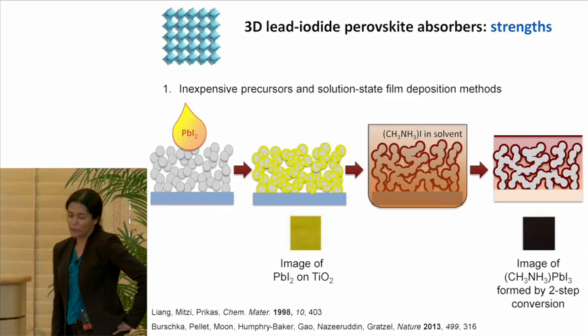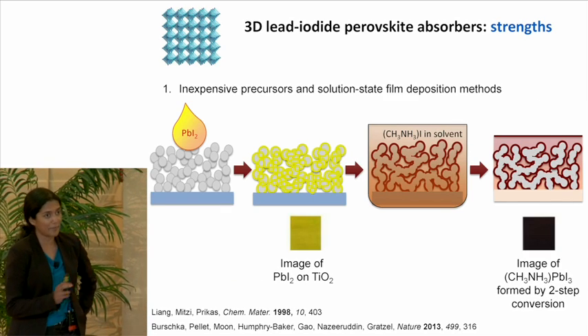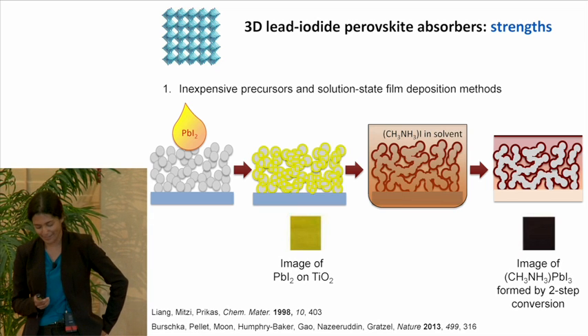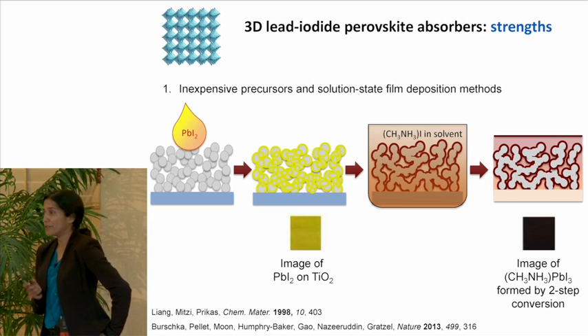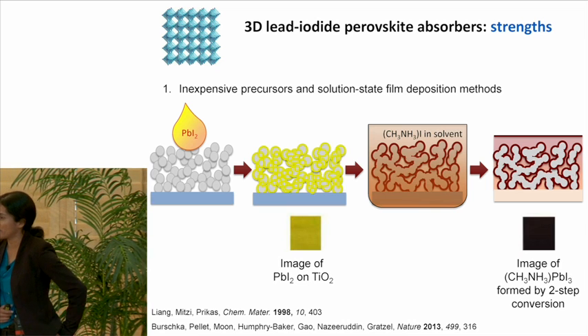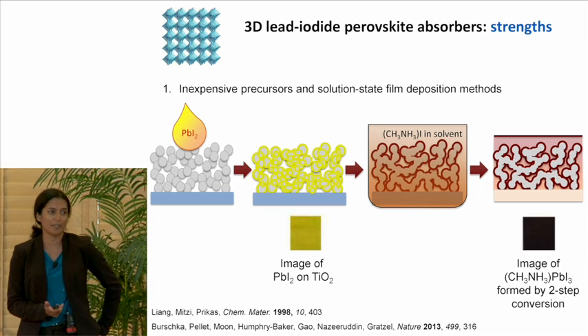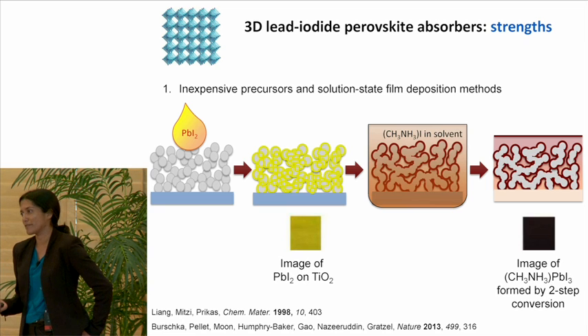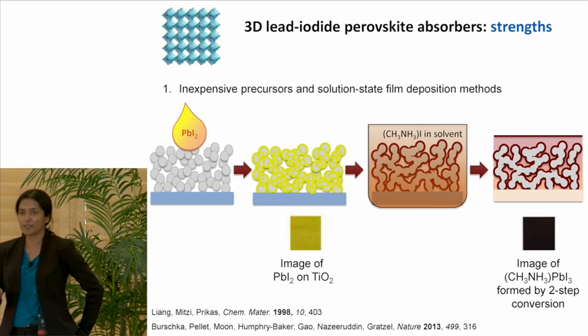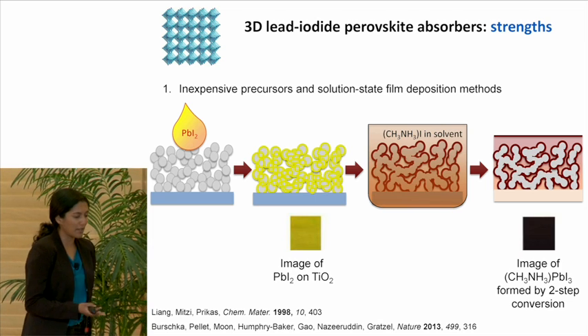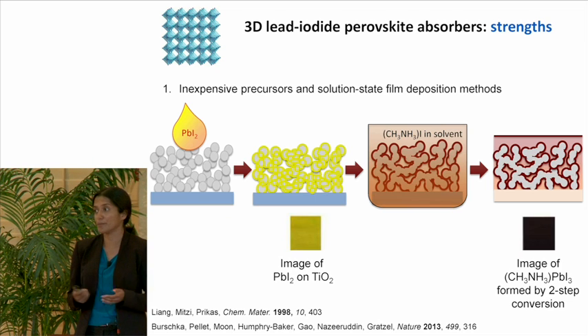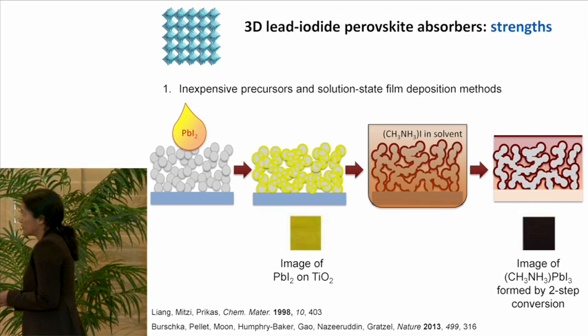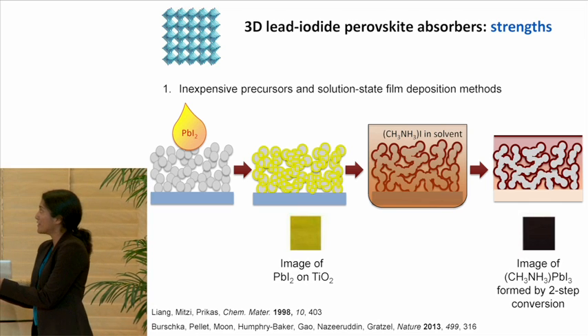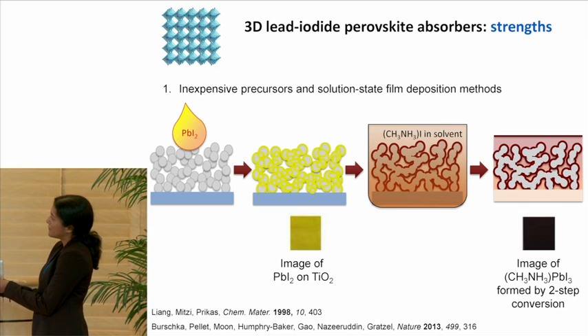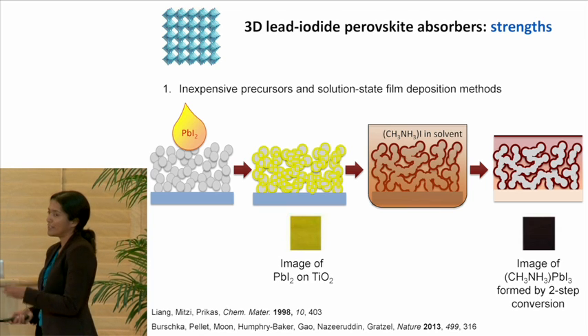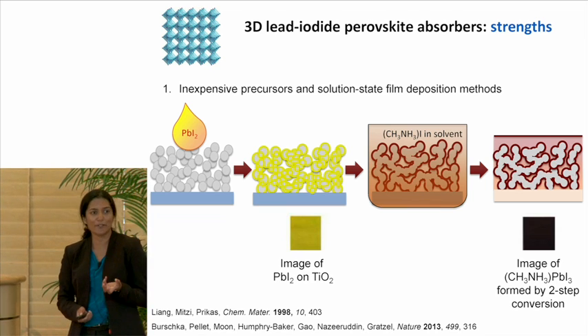So I want to discuss some of the strengths of this material. There are many. I'll just highlight some of the points that I think are worth mentioning. A very important point about perovskite absorbers is that these materials can be formed through solution state methods, which makes everything extremely inexpensive. The precursors are very cheap, and you can use solution state methods like spin coating, drop casting, or vapor conversion methods to make these materials. Here I show you a schematic of one particular way to make nice films of hybrid perovskites, where we can simply take a mesoporous titania scaffold and drop a solution of lead iodide into this material.